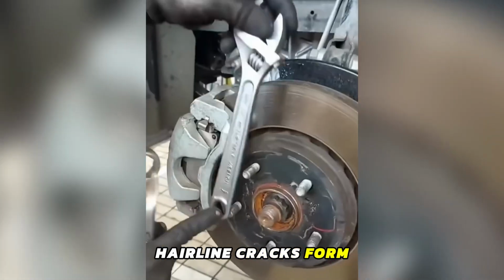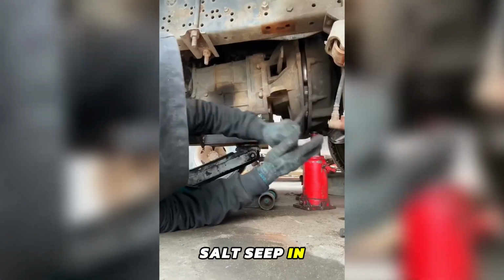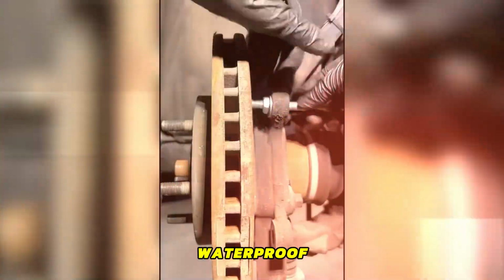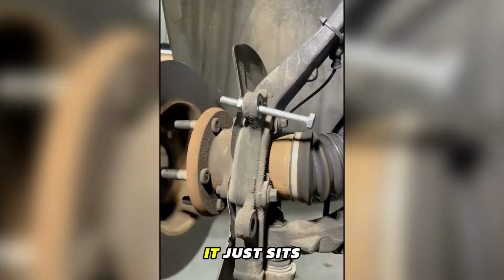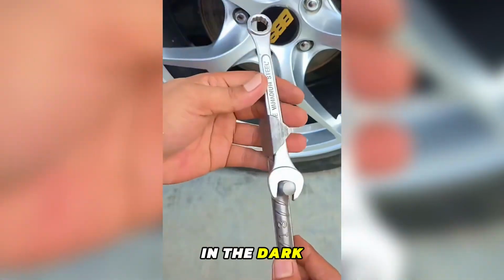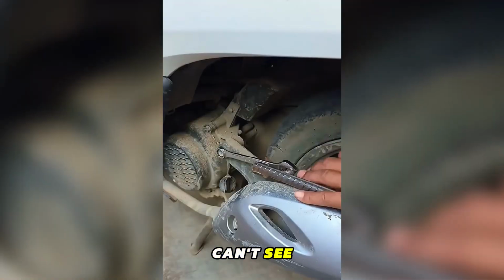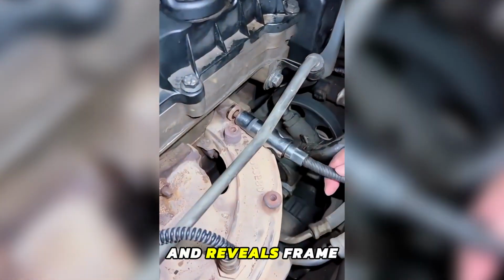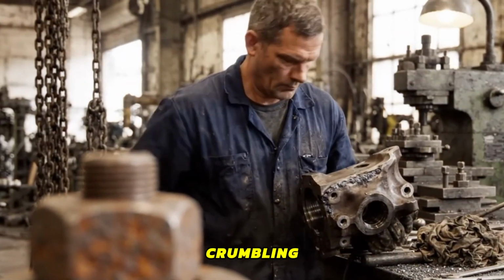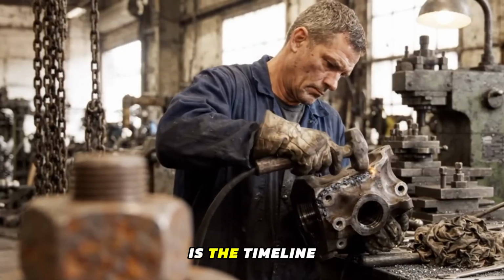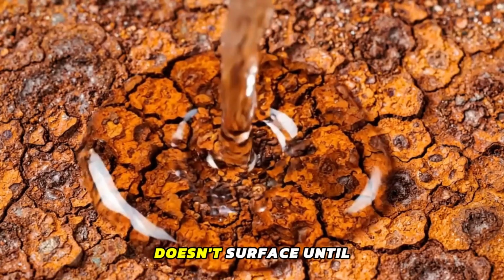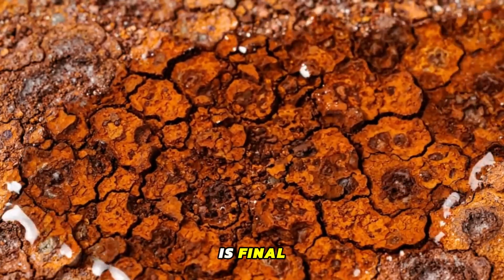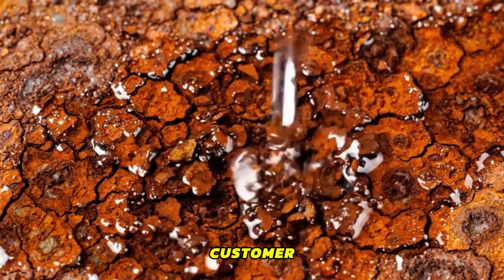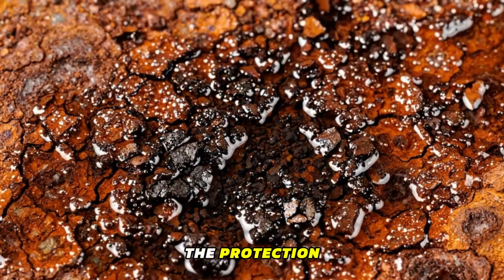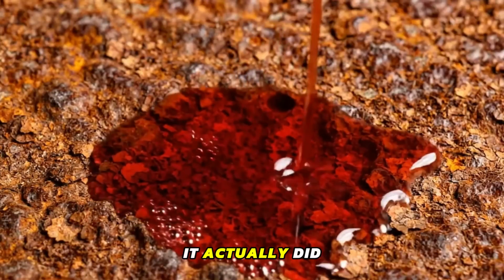Once hairline cracks form, road slush and salt seep in, and because the rubber shell is waterproof, that moisture never escapes. It just sits against bare metal, in the dark, accelerating corrosion you can't see until the coating finally peels and reveals frame steel that's already crumbling. The cruelest part of this trap is the timeline. The damage usually doesn't surface until well after the sale is final and the dealership has moved on to the next customer, so the people who sold you the protection never have to answer for what it actually did.